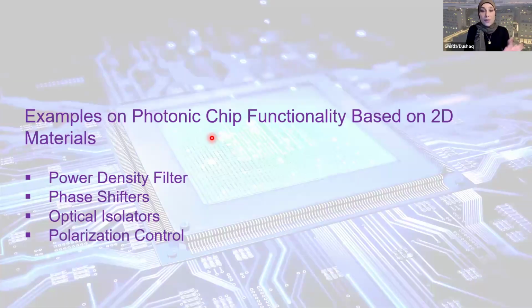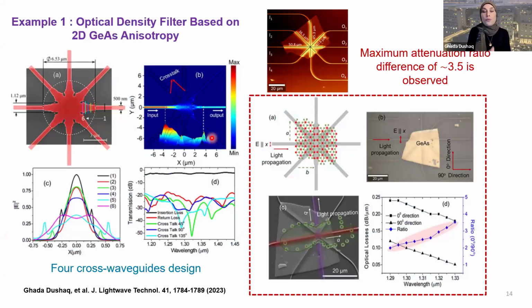I will start with a couple of examples that target different functionalities, depending on the properties this material can be useful for. The first thing is the anisotropy of this material. This material has great in-plane anisotropy. When we talk about optical in-plane anisotropy, the crystallographic orientation has different absorption, depending on the orientation of this crystal.